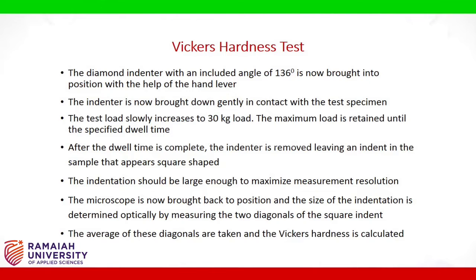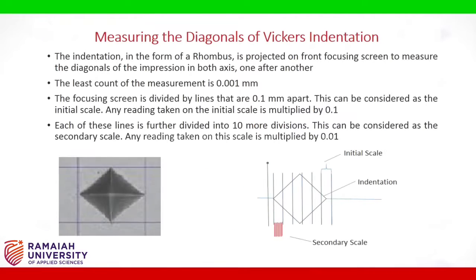The indentation should be large enough to maximize measurement resolution. The microscope is now brought back to position and the size of the indentation is determined optically by measuring the two diagonals of the square indent. The average of these diagonals is taken and the Vickers hardness is calculated. The indentation in the form of a rhombus is projected on the front focusing screen to measure the diagonals of the impression in both axes one after another.